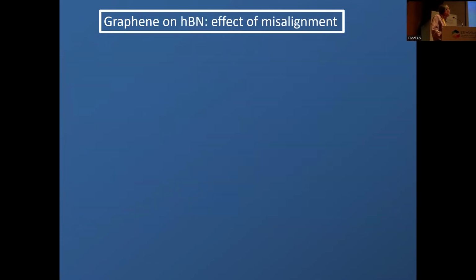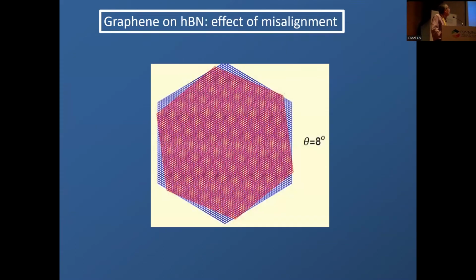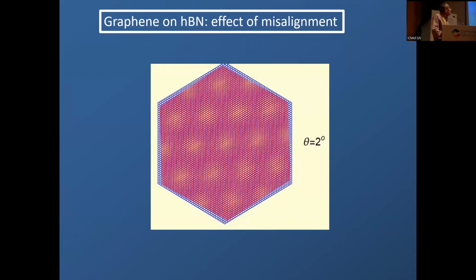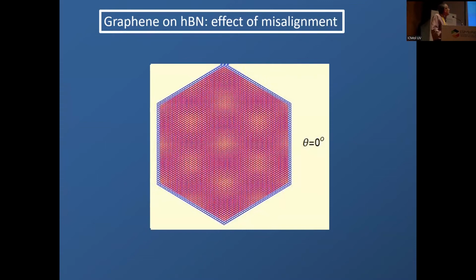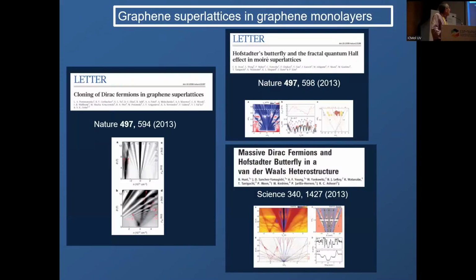This is what I mean. So you see that depending on how well aligned boron nitride and graphene are, when they are perfectly aligned, you see a pattern emerging. This is a bit of a cartoon. The pattern is much larger than that. And this pattern defines for you new periodicities, and it's what I said, a metacrystal. This is the best you can get, and that motivated a lot of interesting research, because if you manage to align graphene and boron nitride, which is something experimentalists can do, then you have this large metacrystal.